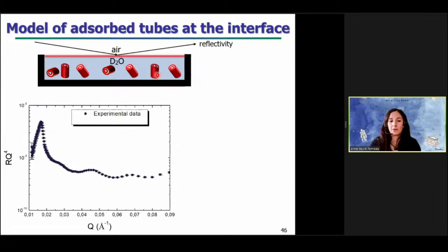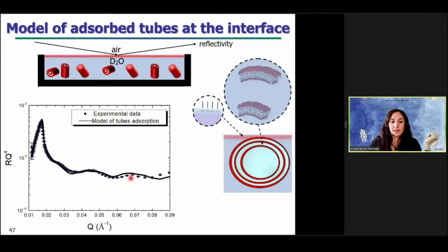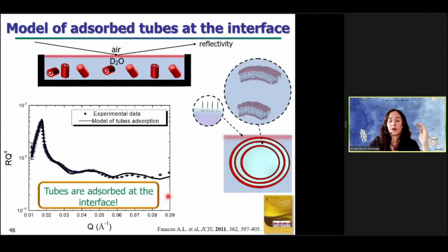And we just compare, again, our experimental data here in blue with our model of tubes adsorption here in black. And as you can see here, the two curves are very similar, showing that tubes are adsorbed at the air-water interface and can stabilize the interface in the same way that solid particles act in the case of Pickering foams.